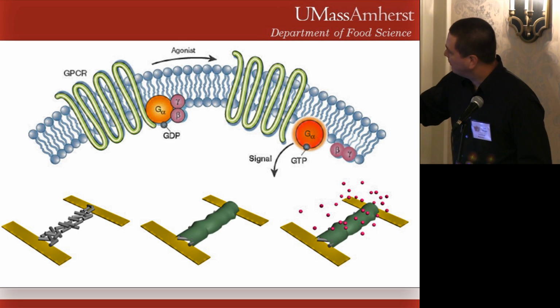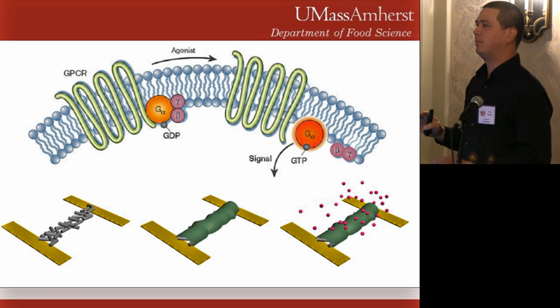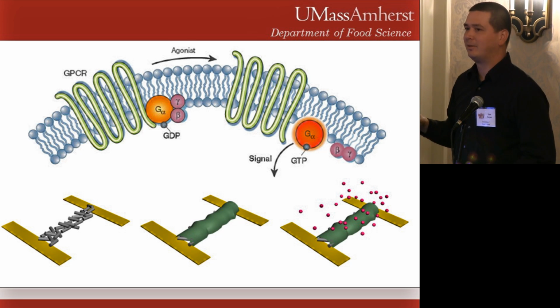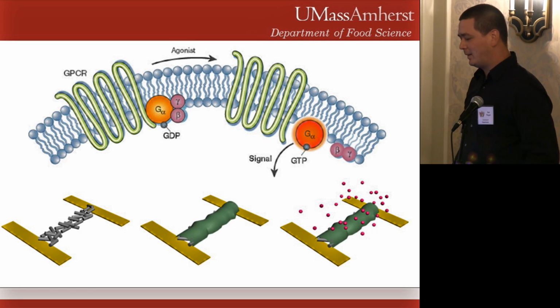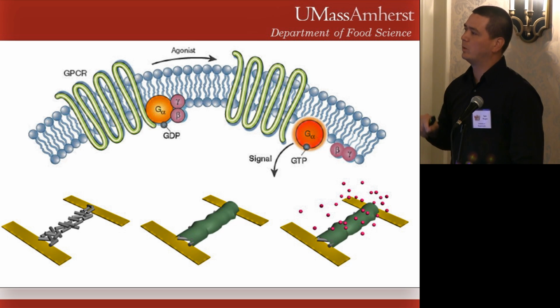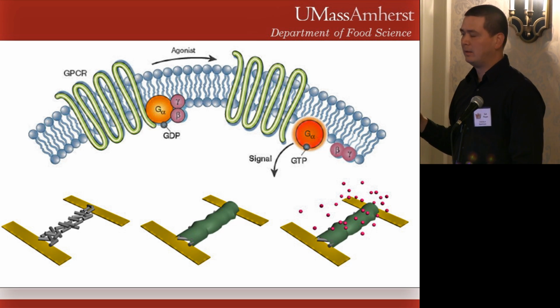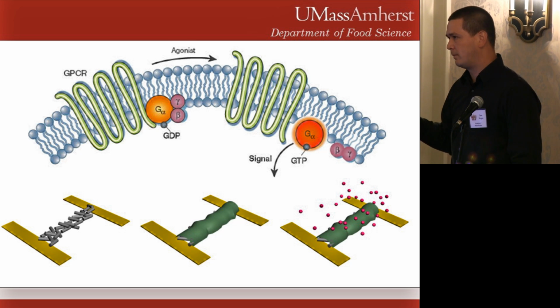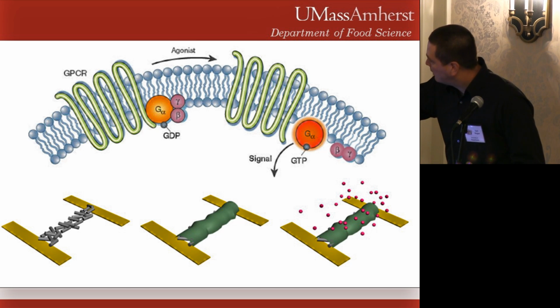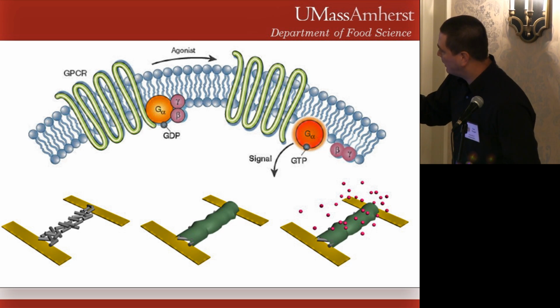What we found is, if we take 2 electrodes here and put conductive nanotubes connecting the 2 electrodes. Now, I should say my research has evolved faster than my drawings have, because now we just have one tube going across continuously like this. But if we put the receptors on these tubes, we functionalize it with the receptors. What we find is if that volatile is near, as we can see in this case, these receptors will start to bind to it and change the conductivity of what's underneath it. So now we can actually measure this binding effect. So we're using conductive nanowires now to do this.